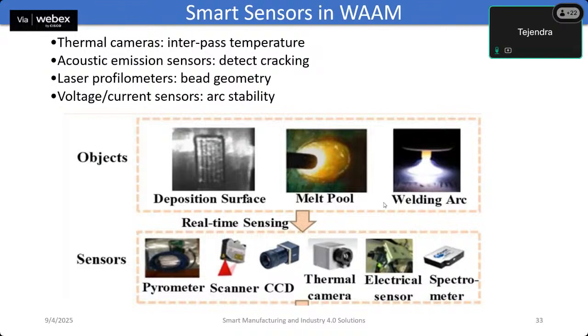Acoustic emission sensors can be used to detect abnormal sound in the arc or the material during deposition. These sounds often indicate cracking or other defects, which can be addressed in real time. The laser profilometer can be used to measure the bead geometry, such as width, height, reinforcement, dilution, or penetration immediately after the deposition, which helps in maintaining uniform layers throughout the process.